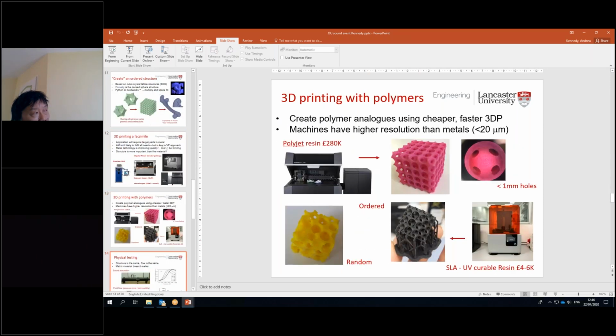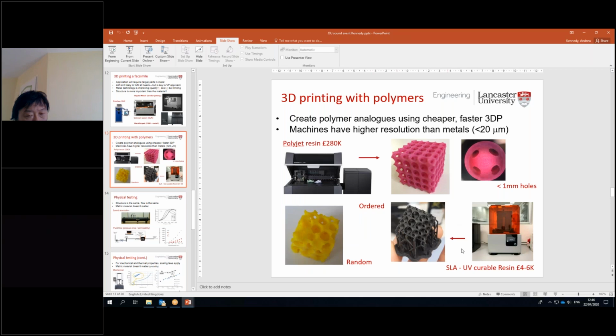Your comments about the printing, I agree completely. We've got a mixture of different systems, and we use a number of different resins to try and improve the removal of the resins, and we can use a number of different flushing systems to try and flush it out. So once you restrict the permeability, inevitably you can have some issues. And we get some quite good results from daylight curable resins as well.